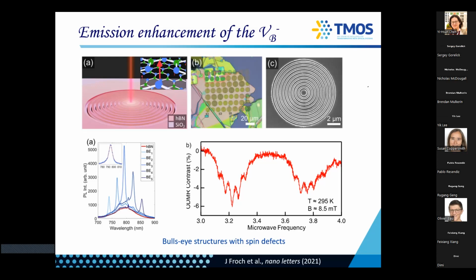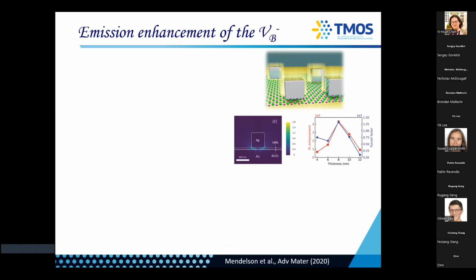You go to a different cavity design. So you go to a gap cavity. A plasmonic gap cavity means that you have a metal and then hBN and a cube on top. And this in principle should give you the biggest enhancement that you can potentially get, about 100 or so. So there's a PL enhancement of about 100, 400, sorry, if you design it properly. So the thickness here is critical.